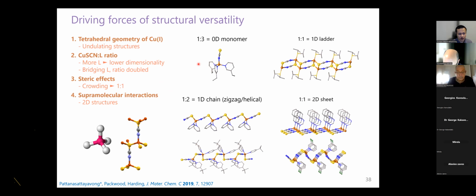The geometry around the copper: it prefers to have the tetrahedral geometry, so we always see some undulation. The ratio: if they have lots of ligands, it basically cuts the number of linkages by the thiocyanate, so with more ligands, we go to lower dimensionality. Also steric effects would prevent too many ligands from joining. And some of the supramolecular interactions appear to have a major role in holding the two-dimensional structures. And 2D structures are very interesting. This is also one of the main directions that we are investigating right now as well.